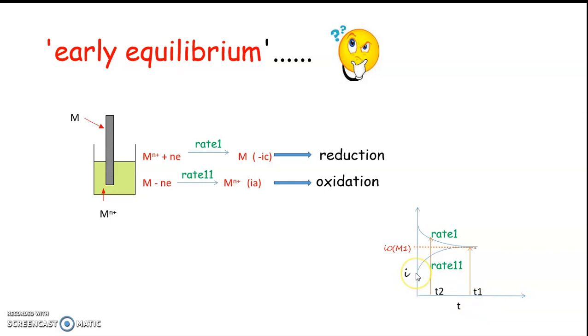When I use platinum, or a metal which can produce early equilibrium, the equilibrium is attained much faster. You can see that as the cathodic reaction starts, suddenly the anodic reaction starts and attains a fast equilibrium, and we get an exchange current density higher than metal 1. This happens for platinum when compared with other metals. So we use platinum metal in the standard hydrogen electrode. If we can produce this difference, that will be the best metal.